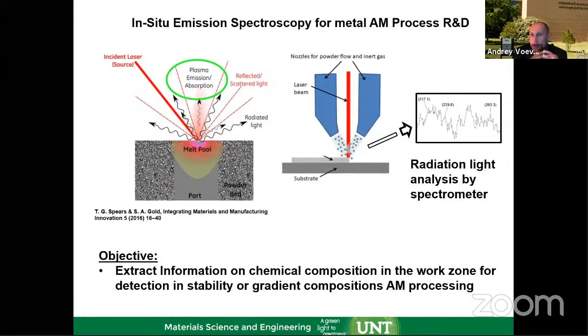When I started translating these approaches to in situ spectroscopy of the additive manufacturing process, the challenge I came across is that on small scales, when you're collecting the signal, the process is not very stable. It is very highly dynamic. When we're doing sputtering, we're removing the target atom by atom, and for a fairly small perturbation, the mass is removed and the intensity is fairly stable. When we're doing additive manufacturing, we bring in the laser and we have a powder, not a solid material. And powder varies in size, right? There are also gaps between the powder, and local density variation where the gap is. And we bring the high energy beam of the laser onto that.